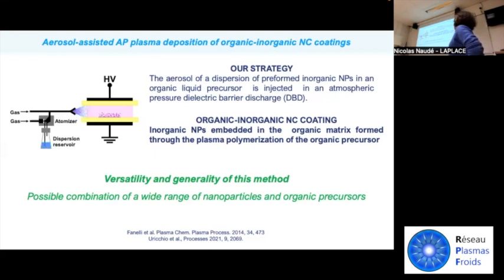And what about the versatility and generality of this method? It relates to the possibility of combining a wide range of nanoparticles and organic precursors. That is, in principle, the process does not need to fulfill the requirements for the in situ synthesis of the nanoparticles in the plasma. This is just a possibility, because there are now new approaches in which it's really possible to synthesize the nanoparticles in situ along with the matrix in a single-step plasma process. But if we need to embed or immobilize on a surface specific nanoparticles with a specific structure and shape that cannot be achieved easily by plasma, this can be a solution, as far as the nanoparticle is dispersible in the liquid precursor.